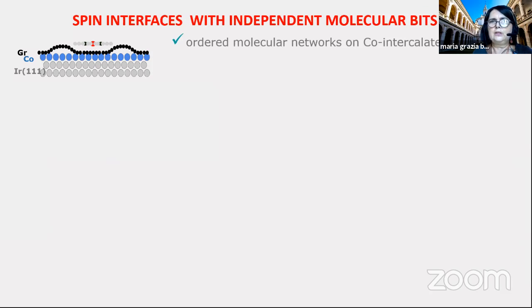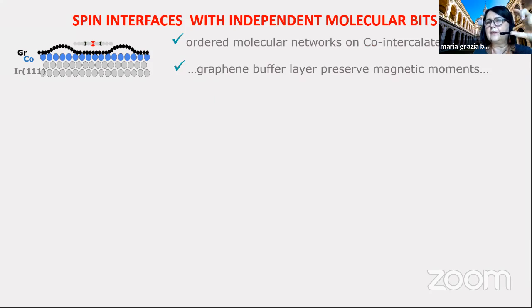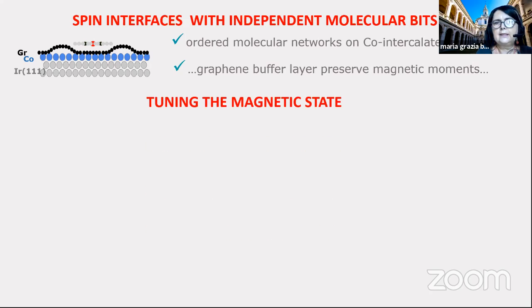We realized the spin interface with independent molecular bits, changing the molecule. So we obtain ordered molecular networks on cobalt-intercalated graphene. This graphene buffer layer is important to preserve the magnetic state of the molecule. So we have an interaction. This is not a direct exchange interaction, but a super-exchange interaction, because it is mediated by graphene. Even though the distance between the molecule and the cobalt layer is more than 5 angstroms, there is a coupling.